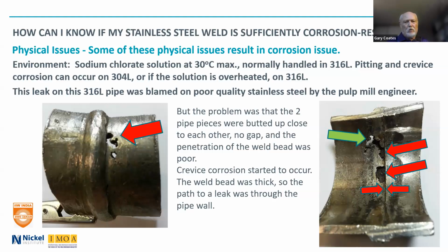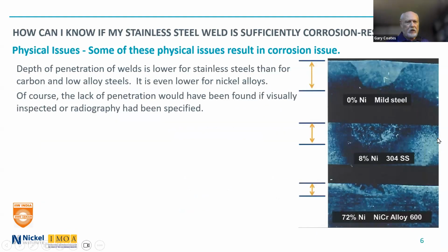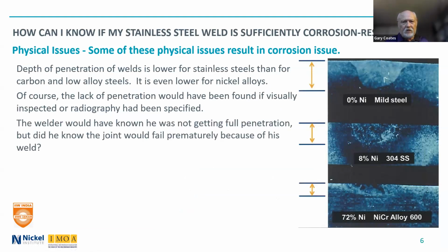So this is where the cause of the failure was welding and insufficient penetration. They did not have a full penetration weld. And as we know, and I've probably said many times, the depth of penetration for stainless steel is less than it is for mild steel, and it's even lower for nickel alloys. But in this particular case, the welder should have allowed a gap between the two pieces of pipe. He probably should have tacked it, which he didn't do, at least on the root side, and welded it.